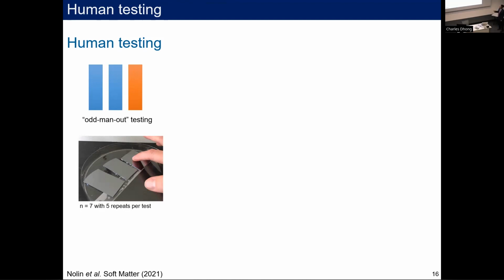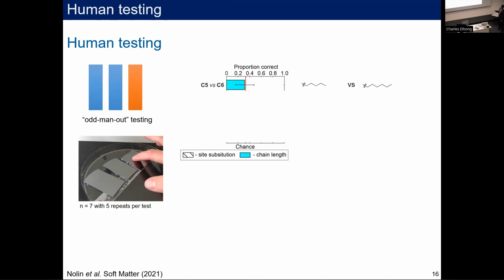So again, what we do is an odd man out test where two of the surfaces are the same. One of them is different. The one that's different is randomized and put in a different location and so on and so forth. But what we see is that if we have these two surfaces, which have a very similar chemical structure, except that the carbon is 1 unit longer, people can't tell that apart. And when we do this internal nitrogen substitution, people cannot tell it apart. But if we make the change in the carbon much longer, so if we increase the length by 3 carbon units, people can actually tell this apart by touch.